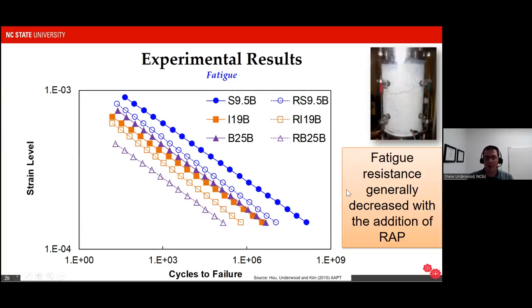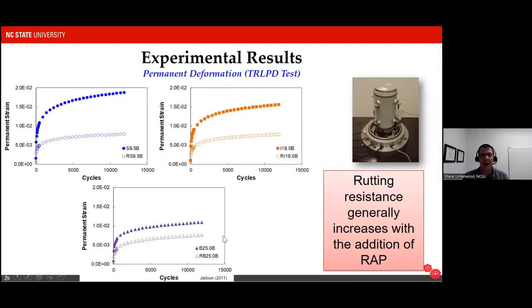When we look at permanent deformation, the behaviors look the opposite. Here again, the RAP-based materials are the unfilled symbols, the non-RAP materials are the filled symbols, and you can see that under the prescribed loading, we accumulated less permanent strain with our RAP-based materials than we did with our non-RAP materials. The exact differences vary whether we're dealing with a surface mix, an intermediate mix, or a base mix.